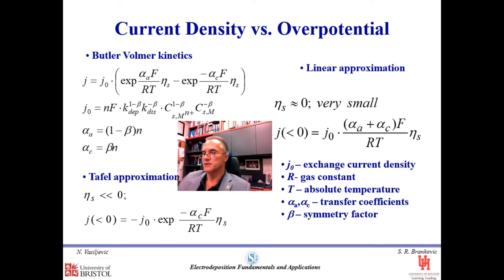Now I would like to discuss the relation between current density and overpotential that we observe during electrodeposition. The most general description of this is given by Butler-Volmer kinetics, where the current density is a function of the exchange current density, and the term in the brackets that is basically an exponential dependence on the overpotential. The alpha A and alpha C represent the transfer coefficients, F and R are constants, and T is the temperature. The exchange current density has a very complicated description. I'm not going to go into details, but just to tell you that this is the part that describes the chemical dependence of the electrochemical reaction, and the term that takes care of the electro part is the one that involves the overpotential.